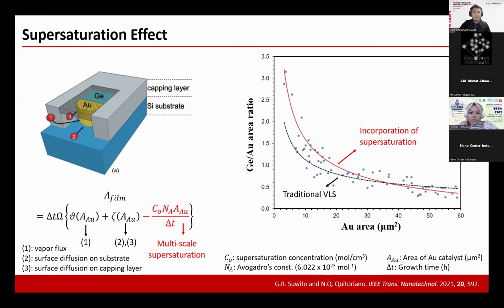So we need to do normalization, and when we try to normalize the data by defining the gold area on the x-axis, giving you the germanium-gold area ratio on the y-axis, you could see that our model, shown in the red curve here, fits better than traditional VLS. So essentially, in addition to traditional contributions from vapor flux 1 and the diffusions 2 and 3, here we introduce what is called the multiscale supersaturation. And here we have the idea that C0, the supersaturation concentration, is the minimum number of germanium precursors needed to make your gold start supersaturation. Because if it's lower than that, it will not be able to start the VLS process.